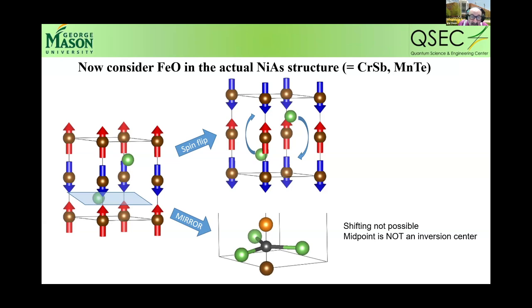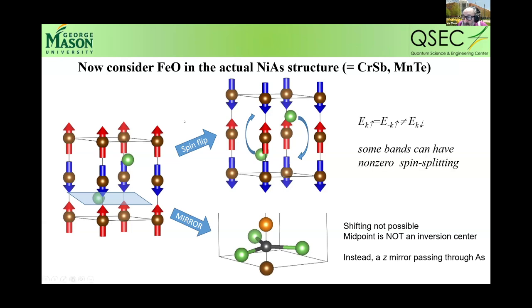But a mirror, and actually no other operation besides inversion, has this property that it conserves the electron energy. So that means that the second part of this equation doesn't hold. So the bands can have non-zero spin splitting, and we know that in nature, if something is allowed by symmetry, it will have it.